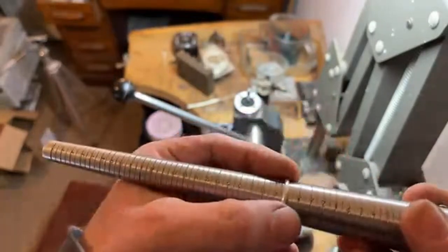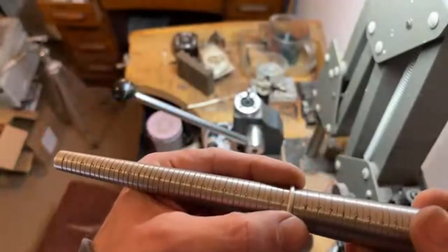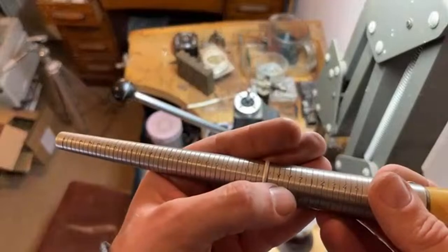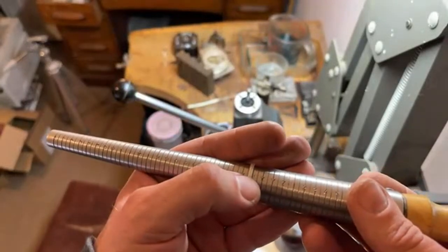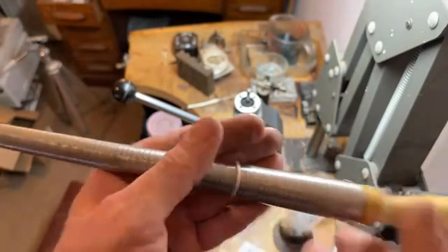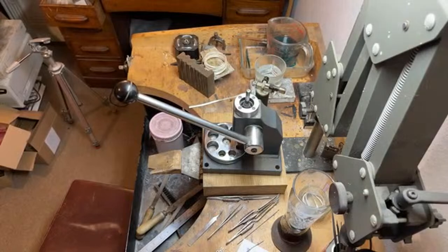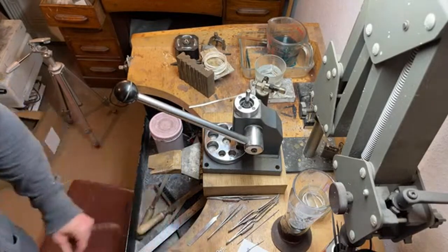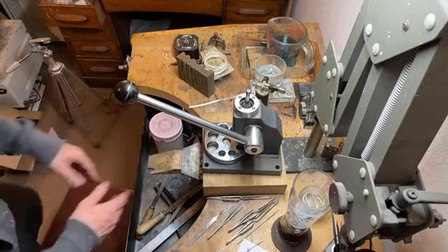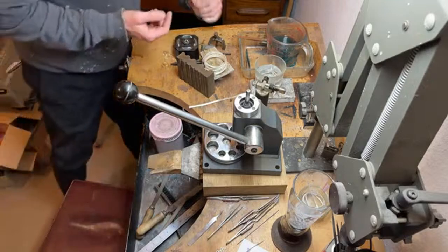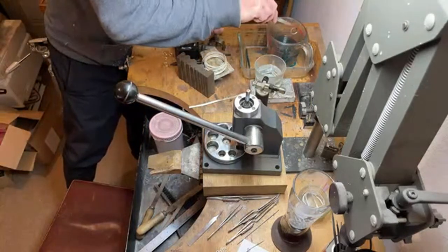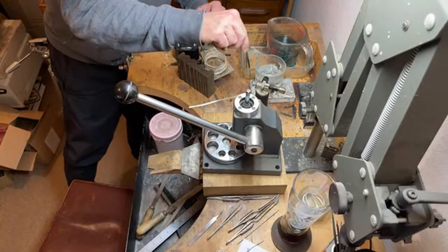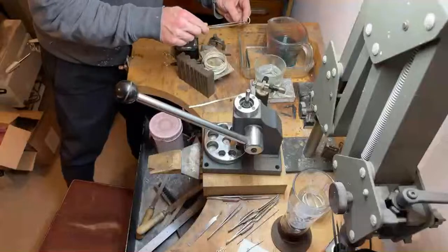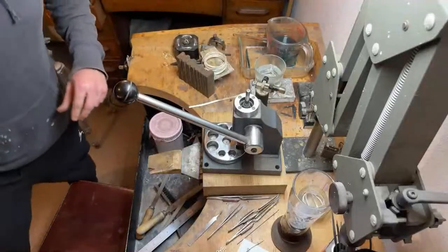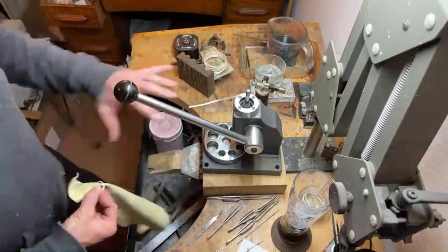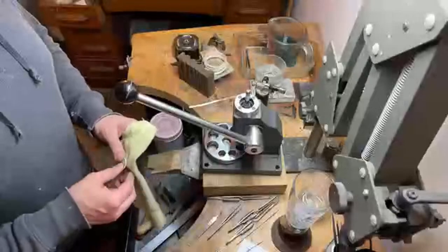And even like, the distance between the W and the X is probably 1 millimetre in diameter. So how that translates, the width of that engraved line to the overall circumference from one side of the ring to the other, we're talking fractions of a 0.00 something of a mil. But if you're doing a 4 mil, 5 mil, you can end up with one side half a size bigger or smaller than the other, which is something you have to work out and understand. You basically have to flip the rings.